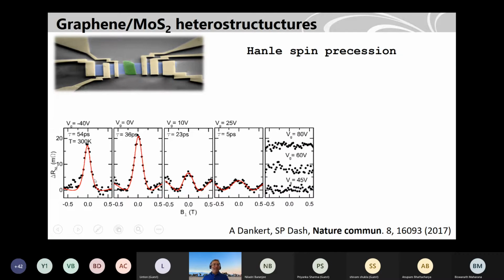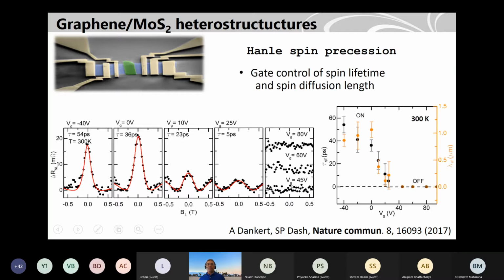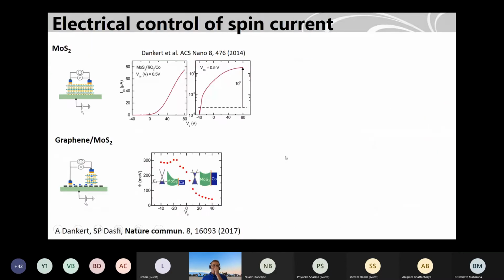And we could also do the Hanle spin precession experiments, where the signal strength is going down and the lifetime also comes down. We can estimate the spin lifetime here with the gate voltage. The signal goes down, then we cannot actually see the signal, so we cannot estimate any lifetime. And why is this happening? We thought about that.